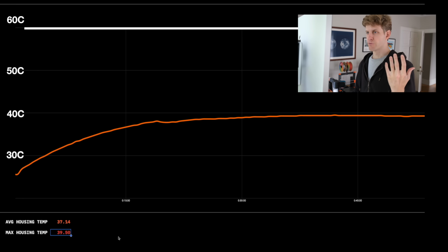This is actually the maximum. So the max housing temperature is the one that we want, and we never surpassed 39.5 degrees. If you look at the internal sensor, it would say 39.875 was the maximum, but still under 40, which means we're 20 degrees away from the glass transition temperature.